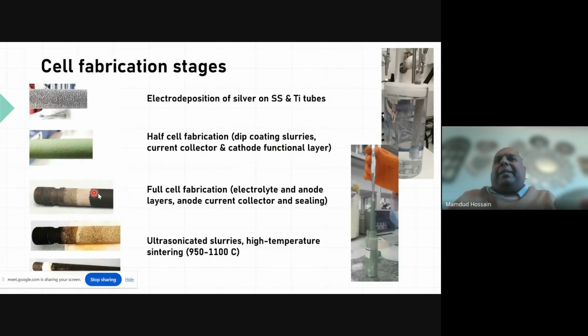So you can see 3 different layers here, because we didn't do the coating 100%. So this is our cathode, which is exposed. This is our anode, which is also exposed. So we can have a current with this surface and with this surface. Okay, so these 2 layers we did with dip coating here. We are doing it by hand, dip coating, and then we have to do sintering. Also we mixed up the slurries in an ultrasonicator, and high temperature sintering. These are the processes we did.